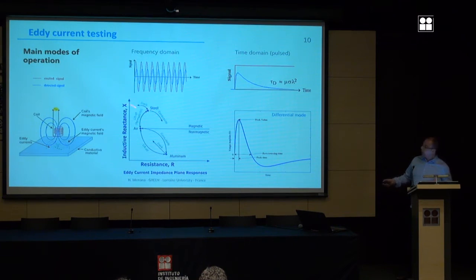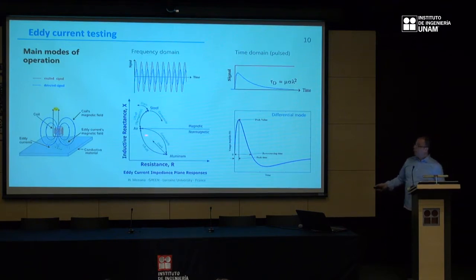The presence of a crack will induce a variation in this direction, and the presence of conductivity will lead to a diminution of the reactance, because the eddy currents will oppose the source magnetic field, and then the reduction of the coil. So we go down here. If the tested material is conductive, we go here. For example, here is the response for aluminum.